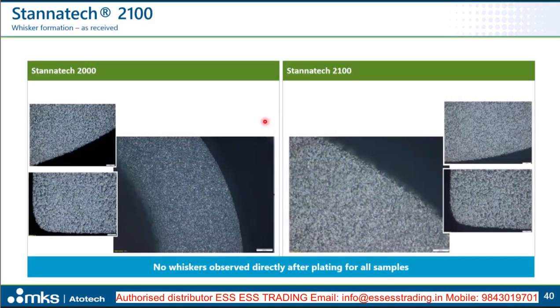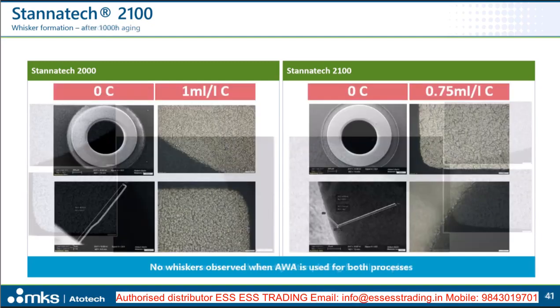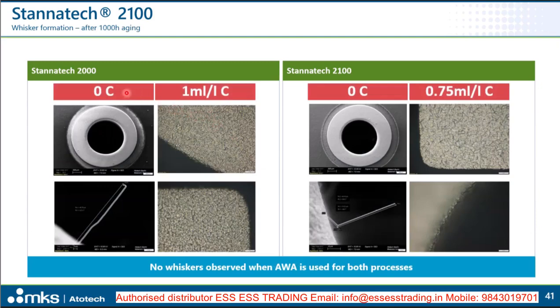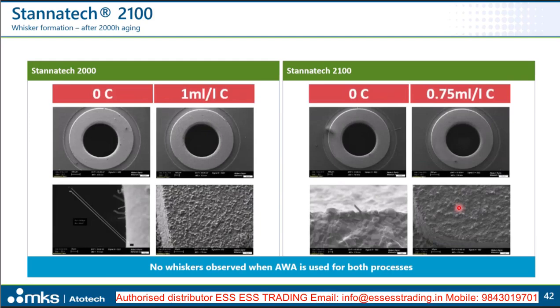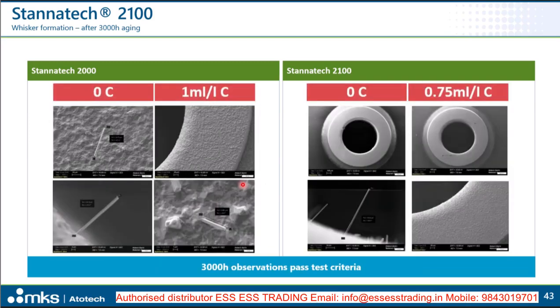And this is now just showing the results for the 2000 versus 2100 in as-received conditions. There we don't see any whiskers. We in particular check this in PTHs, where you typically see them easily and first. Then we did comparisons without the anti-whisker additive and with the anti-whisker additive, and we see that without it, we see some whisker formation in the PTHs. With the additive, the surface is defect-free, so there are no whiskers detected. Similar after 2000 hours aging. Again, we see some whiskers formed with a 0, but as soon as we have additive inside, no whiskers are formed, and similar for the 3000 hours aging.